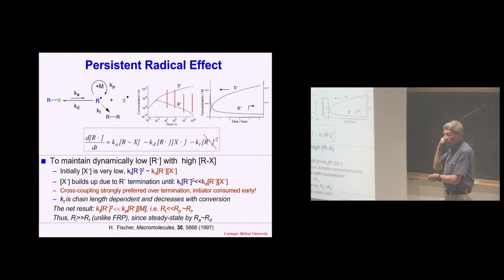So this is a very unusual situation. It follows a pattern. You could see here it's a log-log scale. So what happens here, this is essentially 10 seconds. This is 3 hours. This is 3 months. And this is 300 years. So it's a log scale. It looks really like a straight line. But on a linear scale, you would see that concentration of radicals will jump and then practically become constant. And this persistent radical concentration will progressively increase.